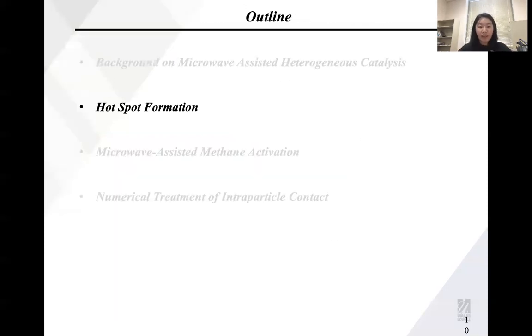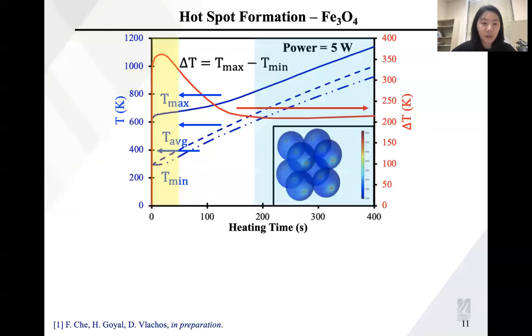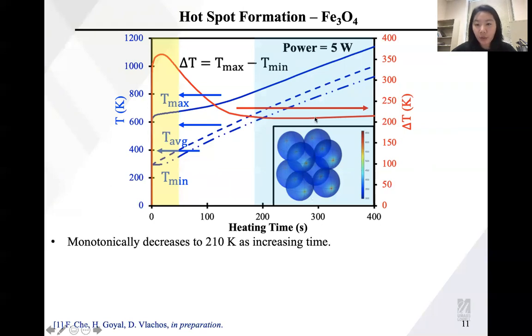Okay, then the next part we will talk about the results on hotspot formation. What kind of factors can lead to hotspot formation? We did a simple example case, which is iron oxide, because we know the dielectric constants and material properties of iron oxide. We found that with iron oxide, it can form this hotspot, and as you increase the time, it can hold a constant 200 degrees Celsius difference between the hotspot and the rest area of the catalyst particles.